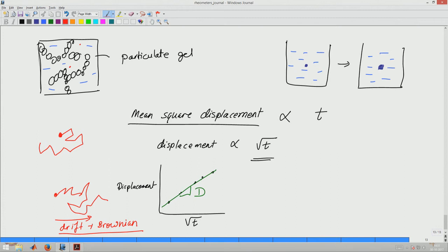In fact, this is one way to check, when we are doing these microscopy experiments, if you do MSD and you see that there is a preferential motion always in one direction, because of the fan or because of the air conditioning or because of whatever other drafts, in fact there are some currents in the fluid, and these currents are forcing all the particles to move in one direction, which is like the shearing that he was talking about. So, in addition to random Brownian motion, there will also be a drift velocity.